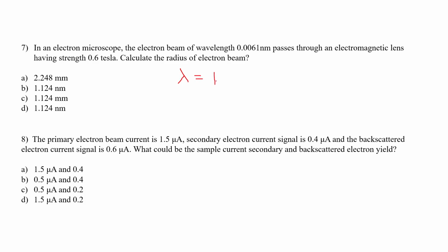The lambda will be given by 150 by V, whole to the power half, and here the lambda is in Angstrom. Please remember it. Now your lambda is given. You need to calculate the energy in volt or kilovolt. Please calculate it using this formula and let me know.